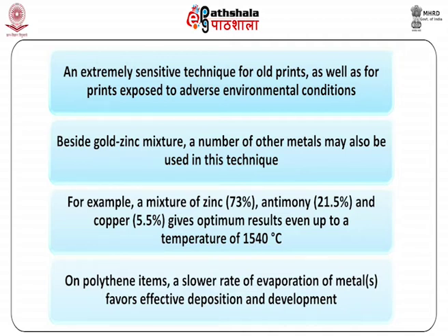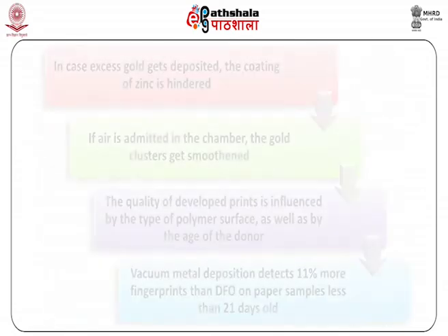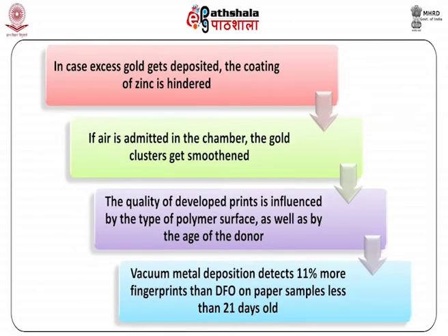Vacuum metal deposition is an extremely sensitive technique for old prints, as well as for prints exposed to adverse environmental conditions. Besides the gold zinc mixture, a number of other metals may also be used in this technique. For example, a mixture of zinc, antimony, and copper gives optimum results even up to a temperature of 1540 degrees Celsius. On polythene items, a slower rate of evaporation of metal or metals favors effective deposition and development. In case excess gold gets deposited, the coating of zinc is hindered. However, if air is admitted in the chamber, the gold clusters get smoothened. The quality of developed prints is influenced by the type of polymer surface as well as by the age of the donor. Vacuum metal deposition detects 11% more fingerprints than DFO on paper samples less than 21 days old.